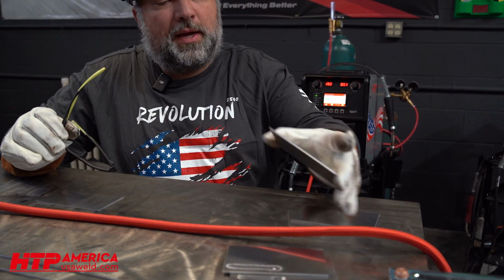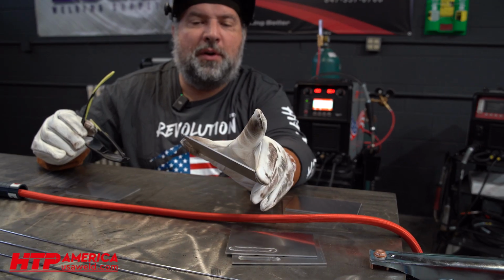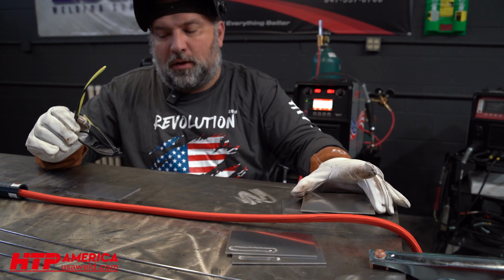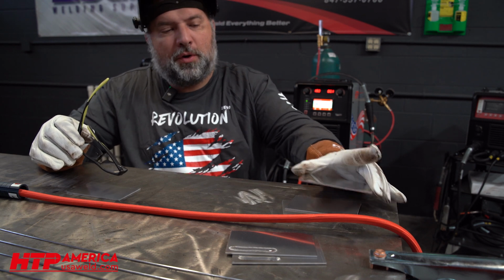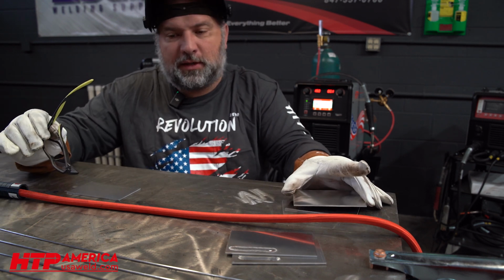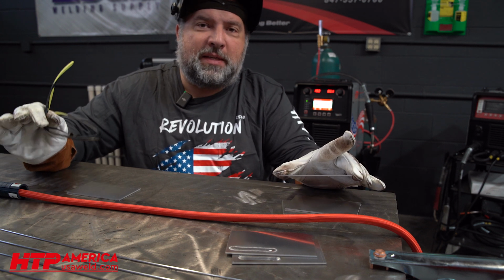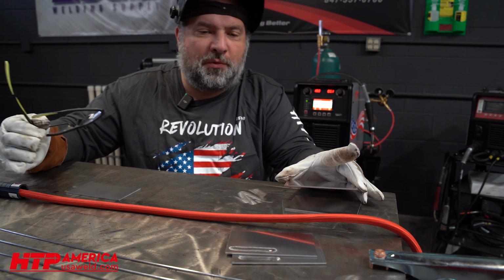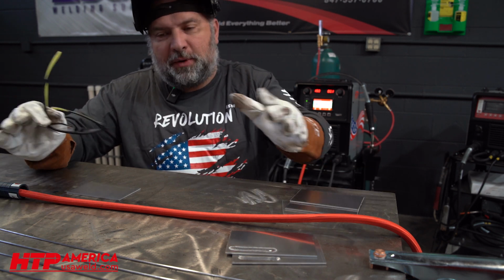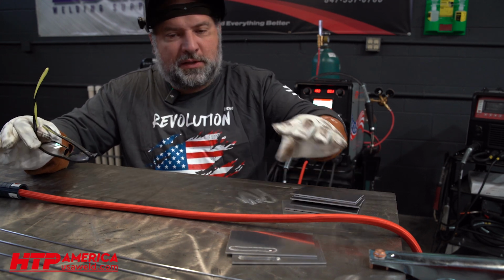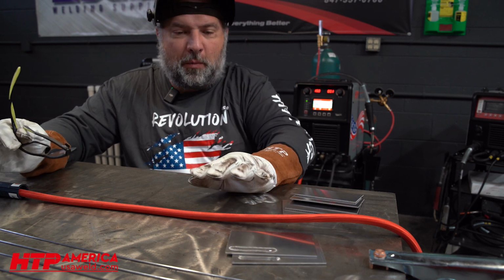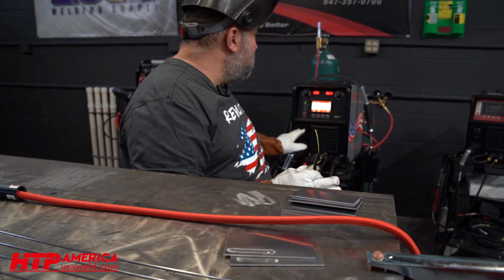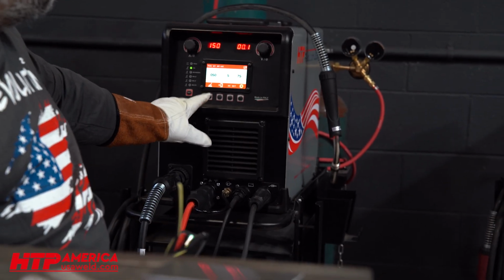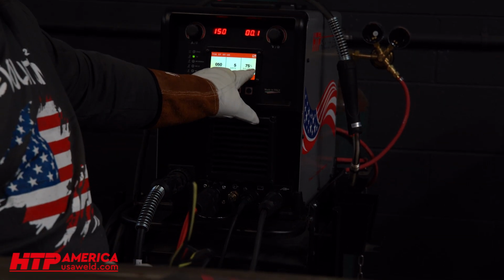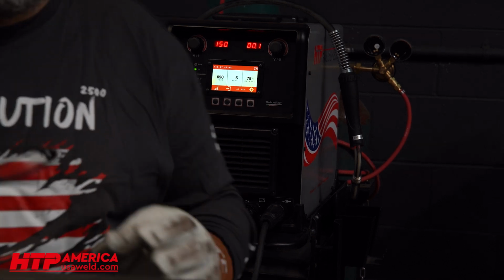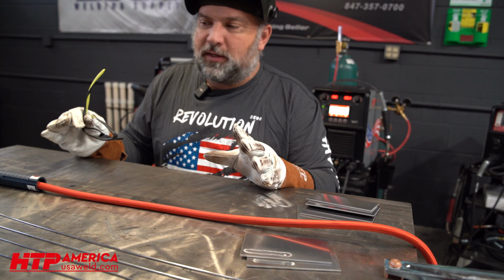The material we're welding on today is 100 thousandths thick, 2.5 millimeter, 5052 aluminum. We will be using a new same-temperature coupon for each one of those rods so that there is no discrepancy in temperature. As the aluminum heats up, the bead lays down differently and contamination is displayed differently. So to keep it an apples to apples comparison, we have 4 coupons, 4 rods, all same temperature. We're going to weld those using the HTP Revolution 2500, 150 amp max pedal, 50 hertz on the frequency, 75% electrode negative on the balance. This way we try to keep the consistency of this test the best we can.